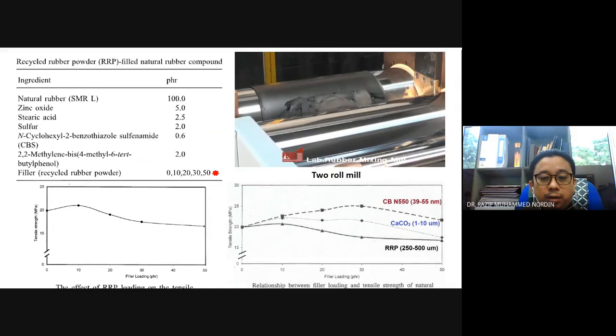And from there, you can get test results, for example tensile strength. Even until today, the first article is being used and cited. Why? Quite simple. Because if you're familiar with rubber technology, especially natural rubber without filler, the minimum strength you need to accomplish is about 16, or quite acceptable 19 megapascal. Below that means the way you process is not up to par.